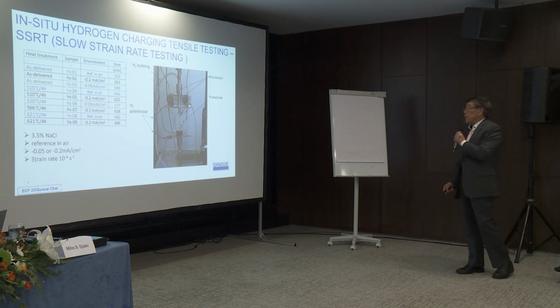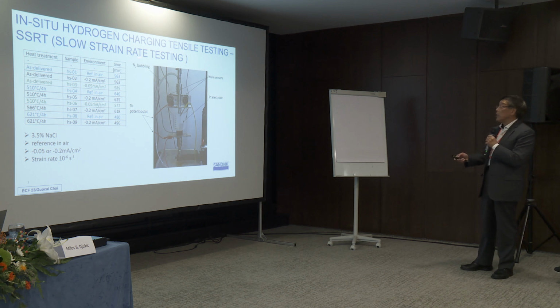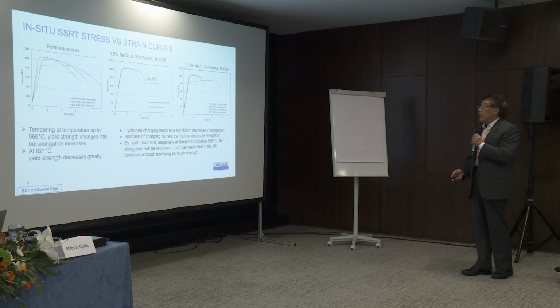So the testing was done in Sweden, with SSRT, slow strain rate testing, a type of testing usually used with hydrogen charging. We use these parameters: 3.5% sodium chloride. Here is important: two currents, one is 0.05 and another is 0.2, with a strain rate of 10 to the power of -6. So here is the result.